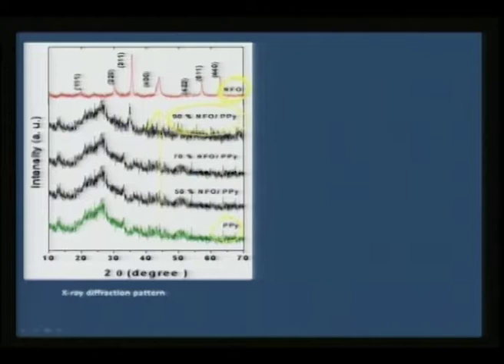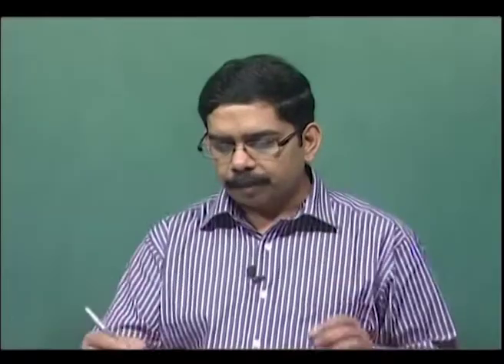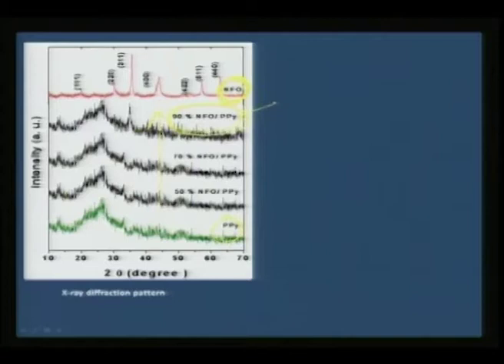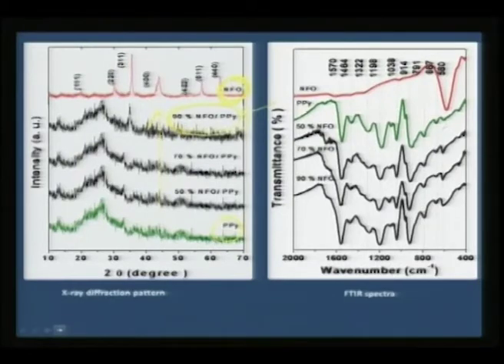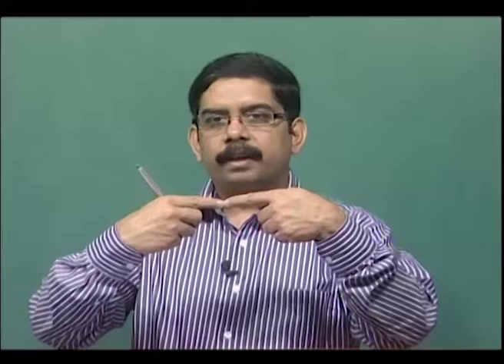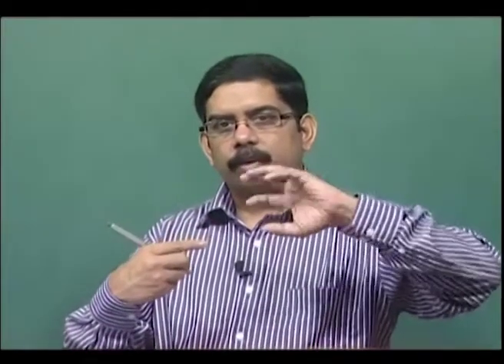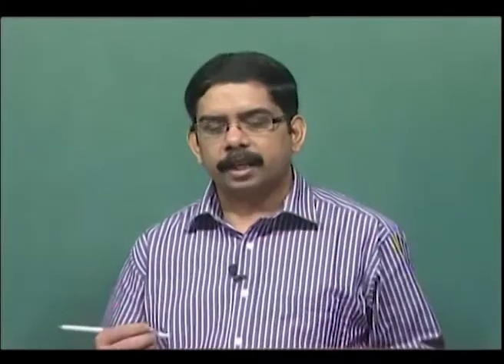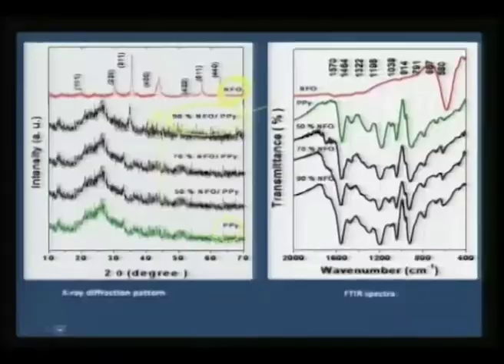As a result, you do not see any X-ray pattern for nickel ferrite, whereas just the nickel ferrite prepared by sonochemistry gives a clear XRD pattern. So, even with 10%, in other words, even with 10% of polypyrrole, you can surface coat these powders effectively so as to mask the crystallinity. So, it is possible to surface coat all these nickel ferrite particles using polypyrrole, and in that way you are actually bringing about a conducting media between any two given nickel ferrite particles, because the outer coating that is happening due to pyrrole is actually a conducting matrix, and this is also clearly proved by the IR pattern.